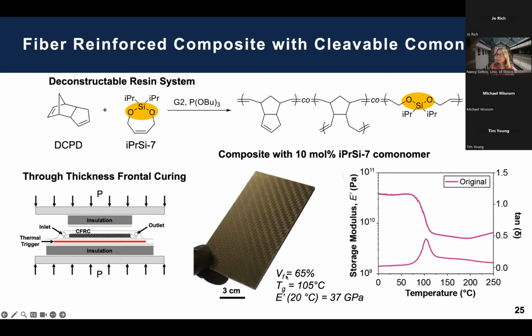You can see that we've lost some properties from initially. We've got a Tg of 105, so still not a bad material. We're up over 100 C for our glass transition temperature. It's got nice properties. It's actually a very nice composite. And I just show the DMA data here on the right, the storage modulus and the tan delta as a function of temperature. So can we deconstruct this?